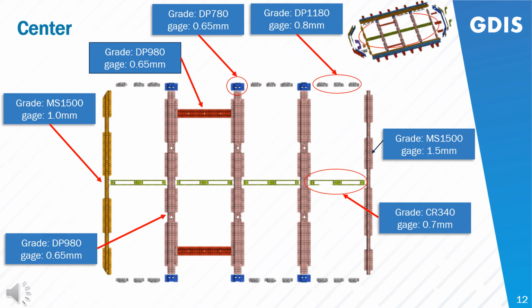Then we have a couple of areas where there are side brackets which are actually used to attach the cross members to the side sill inner, and these are DP 780, 0.65 millimeter thick, while there are other brackets shown in gray, these little brackets that are actually DP 1180, 0.8 millimeter thick, and these are little stanchions for the attachment of the module.